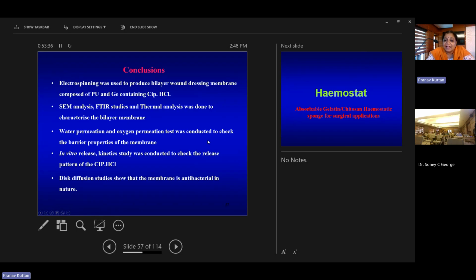So the conclusion is that electrospinning was used to produce a bilayer wound dressing membrane composed of polyurethane and gelatin containing ciprofloxacin. SEM analysis, FTIR studies, and thermal analysis were done to characterize the bilayer membrane. Water permeation and oxygen permeation tests were conducted to check the barrier properties of the membrane. In vitro release kinetic studies were conducted to check the release pattern of the ciprofloxacin, and diffusion studies show that the membrane is antibacterial in nature.